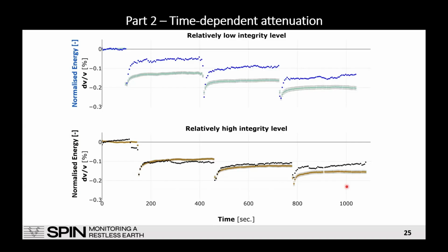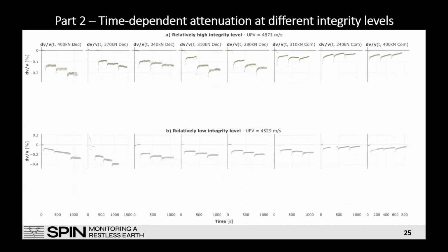So energy is also changing as a function of time. We observe elastic processes happening simultaneously with dissipative processes. This is interesting because there is more information about the nature of the microstructures, and those microstructures suggest that the void volume is changing as a function of time. That suggests maybe the action of opening and closing microcracks in these slow dynamics effects.